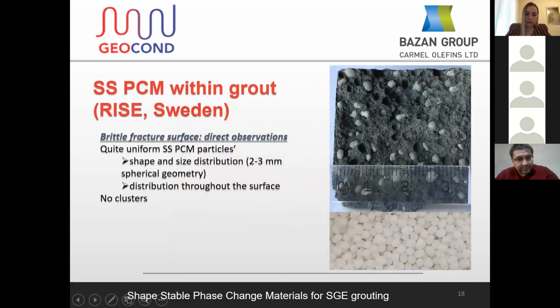Our partners from Sweden spent quite significant efforts and energy developing a composition of grout which can incorporate our material. And the results of this effort you can see here in a comparison of the phase change material before introducing into the grout and after.